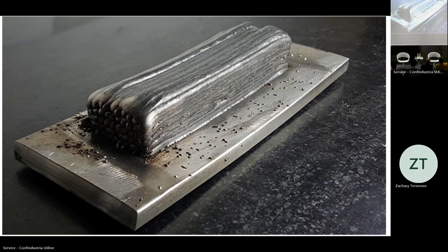Look. Yeah, so the base has become distorted, severely distorted, because the process of depositing layer by layer causes distortion. First you put a hot layer, it contracts. Then you put another layer on top, and so on. So you get a huge amount of distortion, and this is a big problem in 3D printing. Of course this is visible distortion, but you will have residual stresses in the constrained areas, so you need to worry about those.